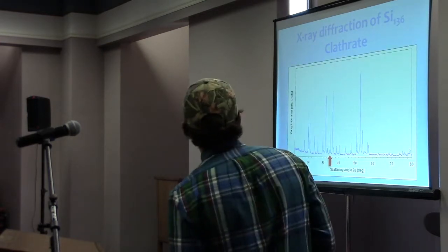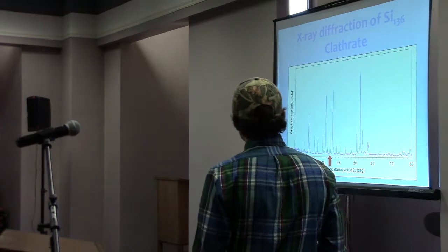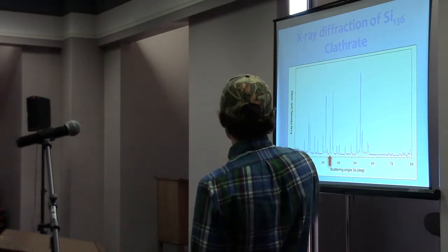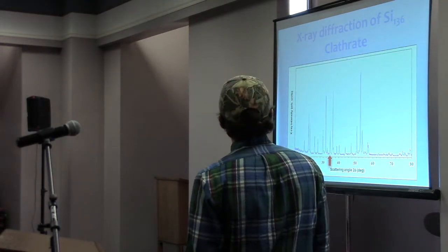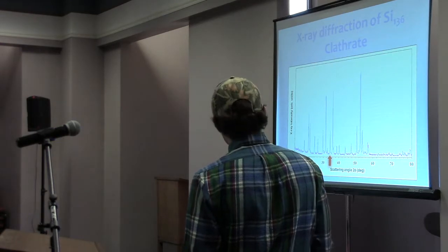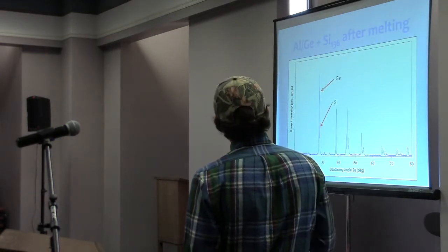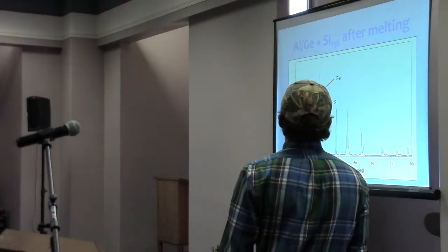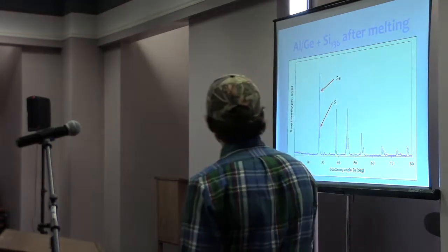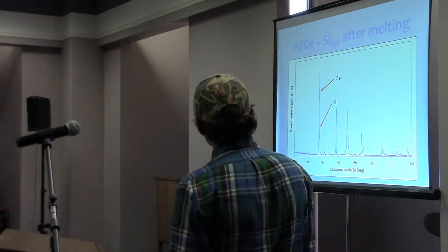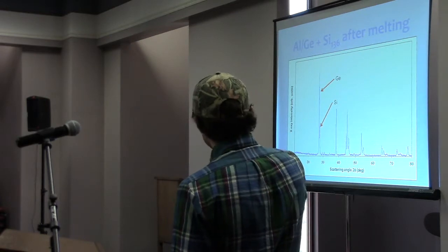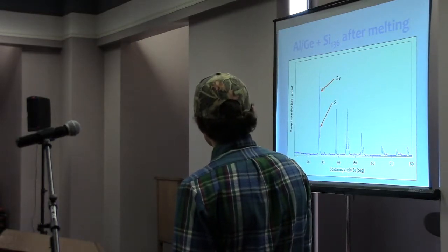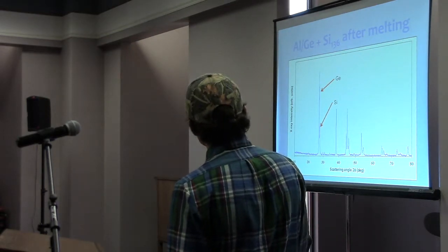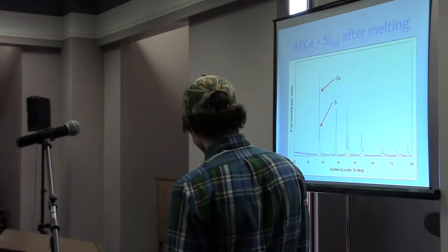So here we have actual X-ray diffraction, and what we're really focusing on is the region between 30 and 40 degrees, where we notice a strong peak of the clathrate. And then, once we created our first aluminum-germanium alloy, including the clathrate, this was heated twice, and we noticed that in the region of 30 to 40, all those peaks are much, much less. And in fact, there's a new silicon peak right next to the germanium.